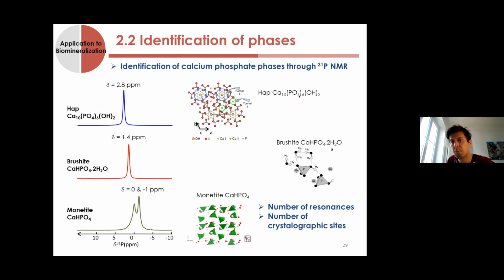Here you have a pure phosphate, here it's hydrogen phosphate, for instance. And of course you see that the chemical shift is different as a function of the environment. Also you have different numbers of resonance according to the number of crystallographic sites in your structure. So that's pretty interesting - it's actually corresponding to a fingerprint of your structure.